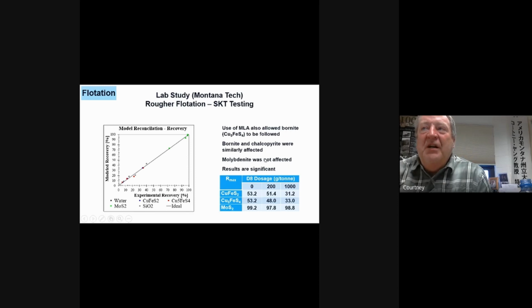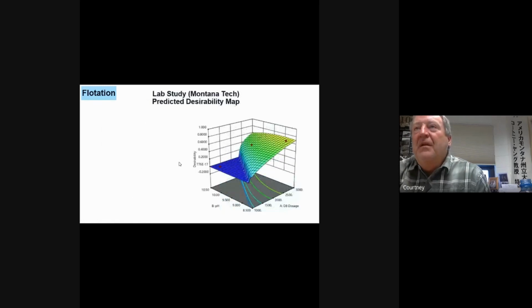Again, molybdenite was not affected, and the results are significant, and I can say that because we can plot our results based on the MLA, and we can model the recovery. And if we have a good model, this should be a 45-degree plot. And you can see that our experimental recovery versus the modeled recovery gives us a 1-to-1 ratio, a 45-degree plot. It's exactly what you want.